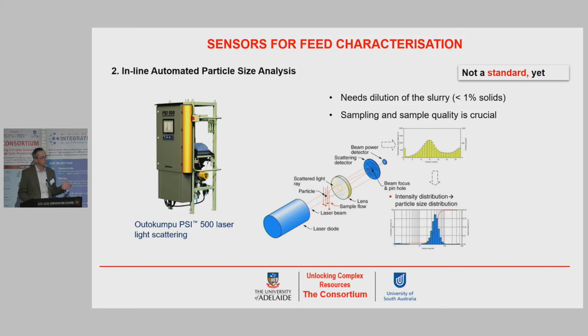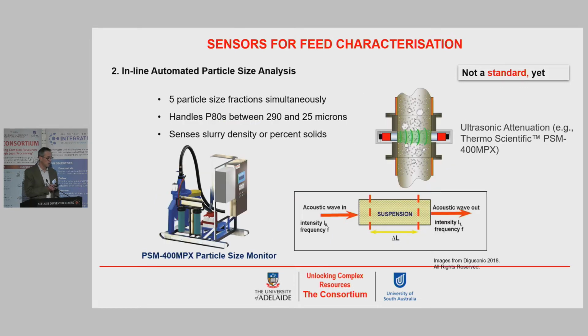It can give a continuous particle size distribution, but at the same time it requires high dilution because laser scattering works at 1% solids. So it's very critical the way you collect your sample for particle size analysis from your stream. And then there is ultrasonic attenuation. As an example, there is the instrument from Thermo, which uses a different mechanism to achieve the same thing, particle size. And there is something there.